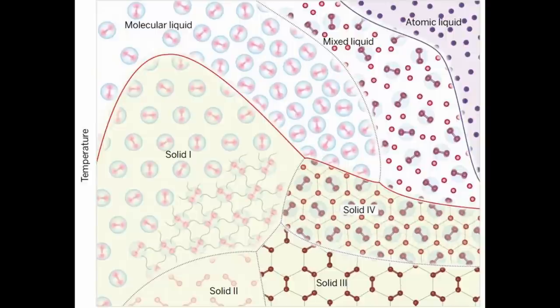Low temperature solidification of hydrogen was first achieved in 1899. An alternative approach is through compression at a temperature of 300 Kelvin. The solid state under these conditions is phase 1. This phase is characterised by quantum spherically disordered molecules arranged in a hexagonal close packed structure. It is an insulator and shows remarkable pressure stability from 5.5 GPa all the way up to 230 GPa.